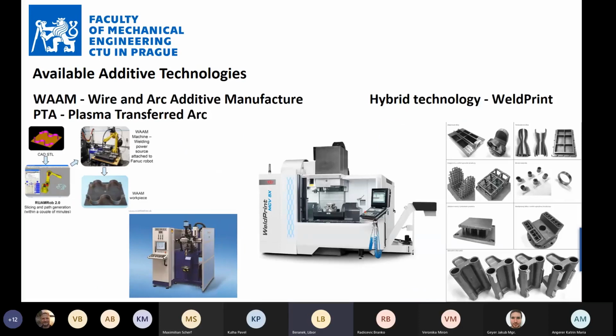I would skip those. And then we have also some special technologies for additive manufacturing of metals, which are based not on powder bed principle, but one of the technologies is based basically on wire and arc additive manufacturing. You can perceive it like MIG welding, which is on a robot or on some kind of portal. And then the plasma transferred arc, PTA technology, where you can combine materials with quite different melting temperatures. For example, you can use nickel alloys, cobalt alloys, and you can mix them basically with boron, tungsten, and materials with very high melting points. And using plasma, you can make quite resilient surfaces or even structures on some kind of material which is usually cheaper.